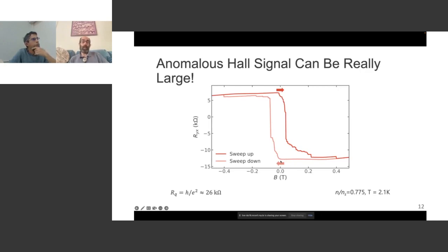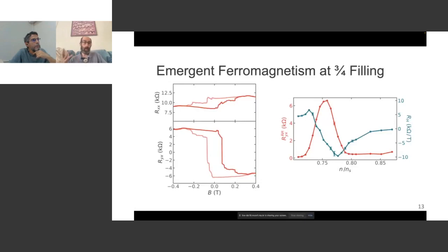So it turns out this is ferromagnetism. We've made a magnet out of carbon, and that's really surprising on the face of it. I mean, normally we think of magnetism as occurring in cobalt or iron or nickel, but not in carbon. It turns out that this large anomalous Hall effect occurs only near three quarters filling of the moiré, where we have three electrons for every moiré cell, or one hole, one missing electron in this band for every moiré cell.